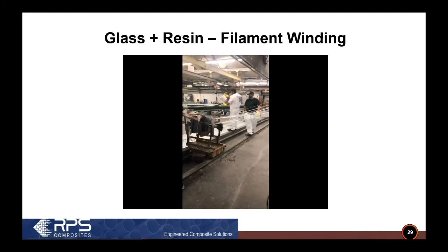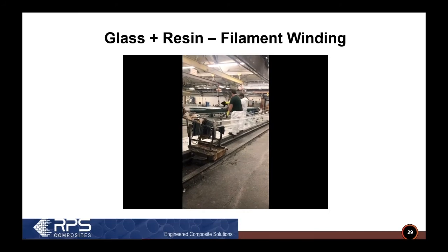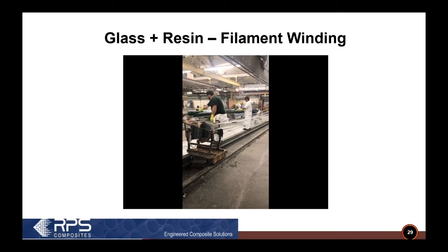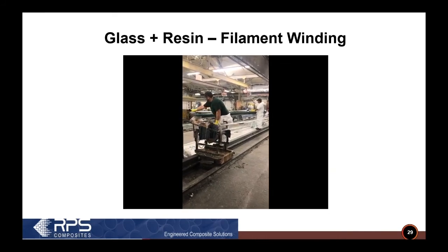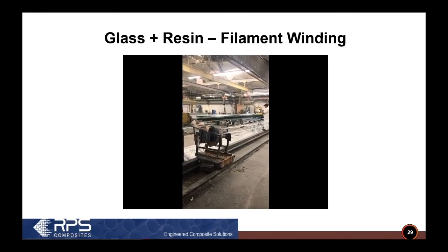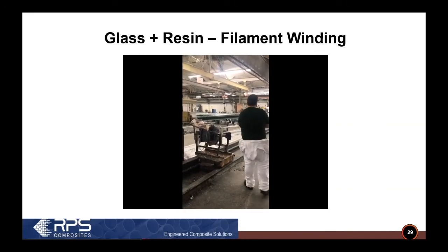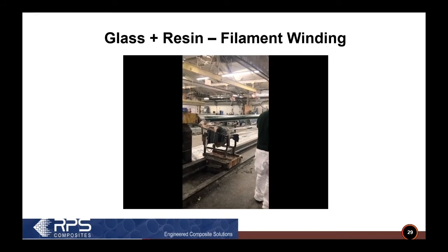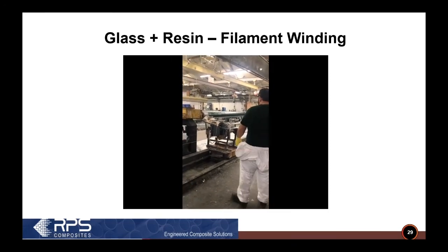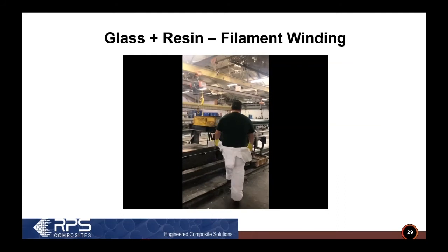So in this case, the operators have already applied the corrosion barrier to the pipe. In this case, the corrosion barrier actually has silicon carbide or aluminum oxide because it's used for an abrasion resistant application. Now they're applying some catalyzed resin over the cured liner to get a bond. They have a predetermined set of rovings, a pattern that runs down into the catalyzed bath of resin. So engineering would have given them the number of rovings to tie onto the carriage. And then they also have a predetermined program. In this case, it's a PLC program that controls the movement of the carriage relative to the mandrel.